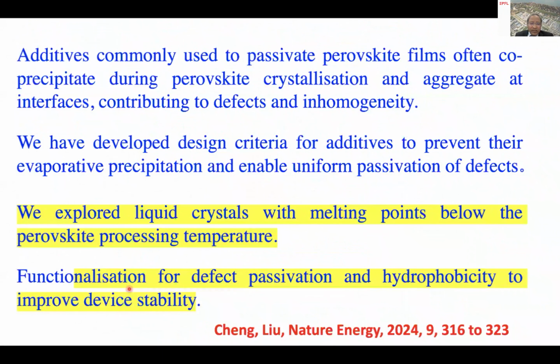Now I come back to another interesting topic. I'm giving all the information for the students so that they can come up with their own ideas. Some of these additives, when you put them into the perovskite, will precipitate at the grain boundaries. And by having this precipitation at the grain boundaries, you increase the recombination. So in order to avoid this drawback,